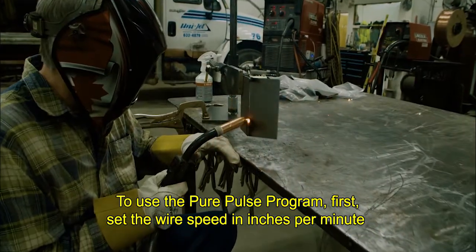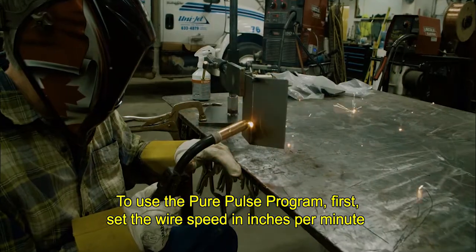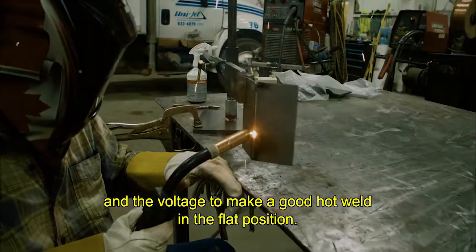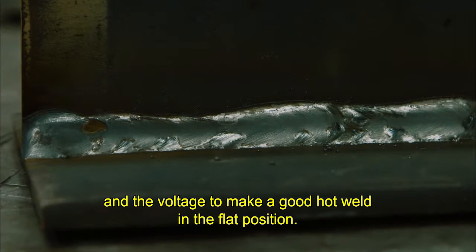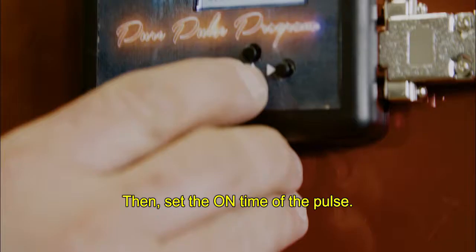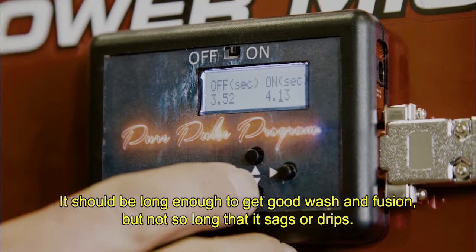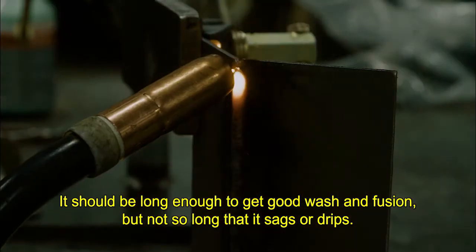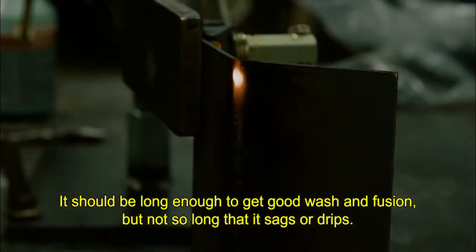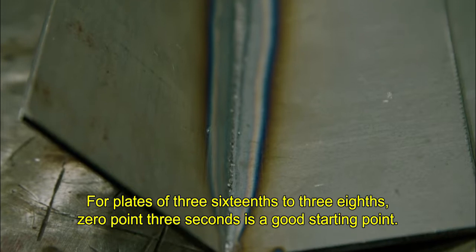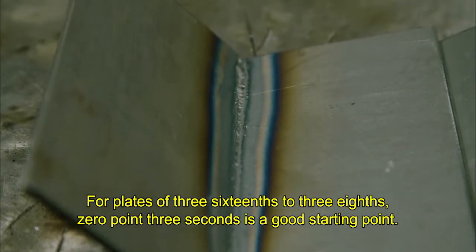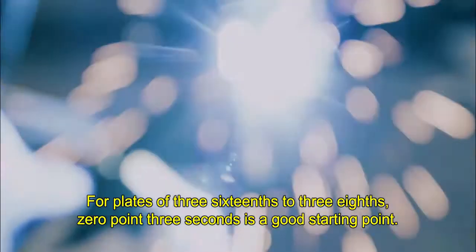To use the Pure Pulse program, first set the wire speed in inches per minute and the voltage to make a good hot weld in the flat position. Then set the on time of the pulse. It should be long enough to get good wash and fusion, but not so long that it sags or drips. For plates of 3/16 to 3/8, 0.3 seconds is a good starting point.